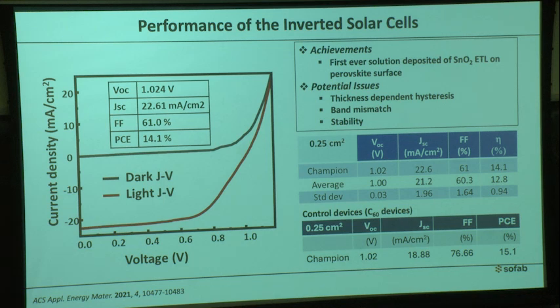The reason people never made a cell before by depositing tin oxide, metal oxide, directly on top of the perovskite in solution phase: people can use other methods like ALD, but ALD is super slow and doesn't have any practical application. This is the demonstration of the first practical application: we can deposit metal oxide directly in solution phase and make a functional perovskite solar cell.